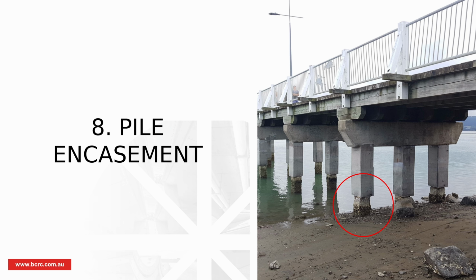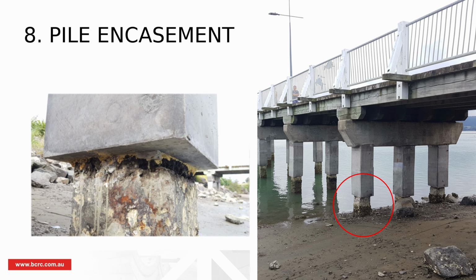Now let's talk about pile encasement, which is probably my favorite topic. I took this picture on a holiday around New Zealand, and what you see here is jackets that were built to protect the existing piles. But from what appears, especially on the picture on the left, the jackets didn't extend as long as you would expect them to, and it's clear to me that about 0.5 to 0.7 meters of the pile just above the low tide wasn't protected, and it does show significant deterioration and corrosion issues.